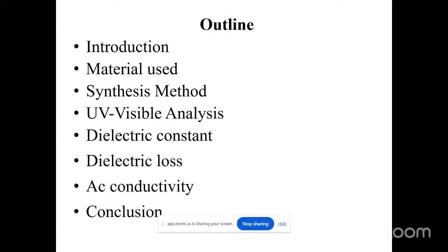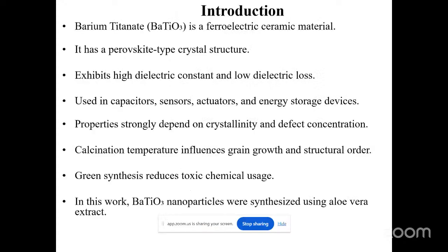First I will briefly introduce the material, then discuss the synthesis method. After that, I will present the UV visible optical analysis and dielectric properties. Barium titanate is an important ferroelectric ceramic material having a perovskite crystal structure. It is widely used in electronic devices such as capacitors, sensors, actuators, and energy storage systems because of its high dielectric constant and low dielectric loss. However, the properties of barium titanate strongly depend on crystallinity, grain size, and defect concentration, which are influenced by the calcination temperature.